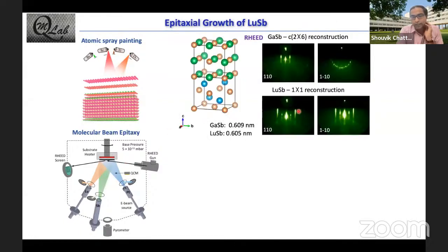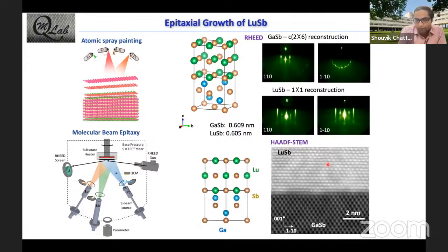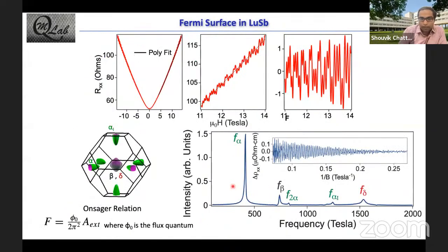Here what I'm showing are the electron diffraction images, which we can take in situ while growing these materials. What you see here is that when we start growing lutetium antimonide, you get a very sharp 1x1 reconstruction, as you would expect for a rare earth mononictide film. We can also look at the transmission electron microscope. Here I'm showing you one such lamella from the heterostructure that we grew of lutetium antimonide on gallium antimonide. I think you can very clearly see a sharp transition from a zinc blende type structure to a rock salt structure. Once we have our film, we can then look at the electronic structure.